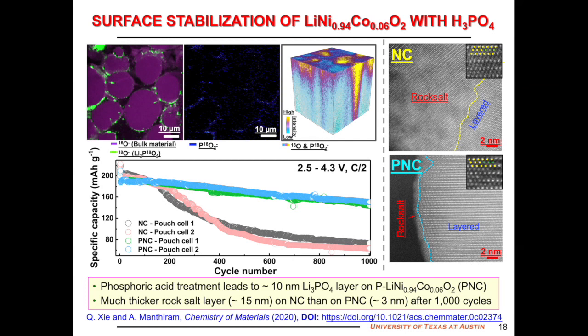We have now surface stabilization by treating these oxides with oxygen-18 enriched phosphoric acid. The phosphoric acid amount is less than 1 mole%, very little. When you do that, it reacts with the residual lithium and forms a nice Li3PO4 layer on the surface. You can see from the ToF-SIMS image. And the big difference you see is the cyclability. The sample PNC means phosphoric acid treated, NC means not treated. You can see much better cyclability when you treat the sample with phosphoric acid, because the surface is covered with a nice lithium-ion conducting Li3PO4.